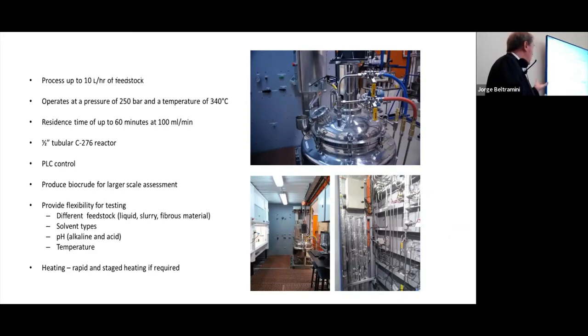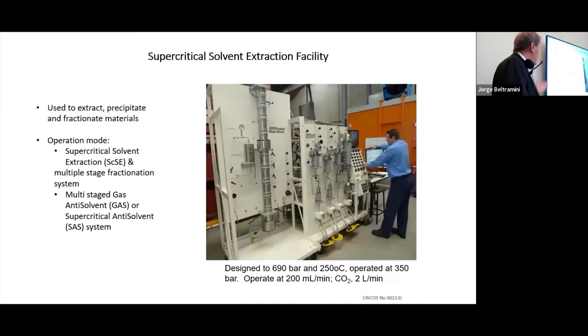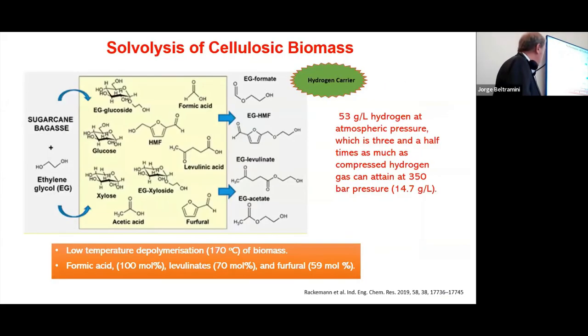And we have a tubular reactor also, and we can process 10 liters per hour of feedstock. So it's a very large plant. The same, we have a supercritical solvent extraction facility when we need to extract the different solvents that we use in order to separate the different fractions.